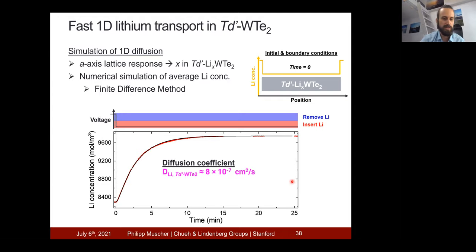So what does that actually mean? How does it compare to related materials? Well, if we look at the two most common cathode materials in lithium ion batteries, you can see that their diffusion coefficient is 6 orders of magnitude slower. So what we found is an extremely fast diffusion coefficient, which makes this a useful system for fast dynamical switching if we only use flakes that have a small lateral size.